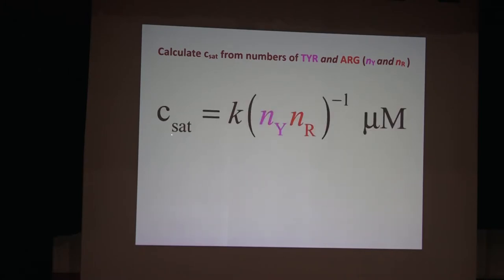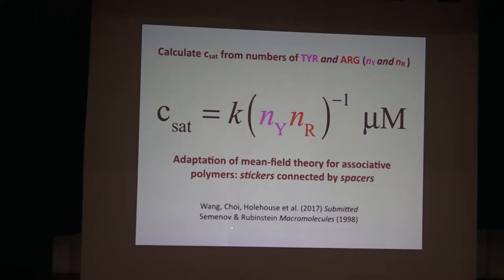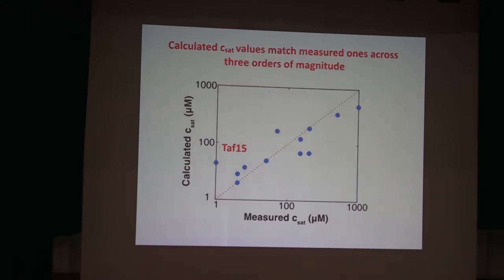You need to go to really low salt — like 75 millimolar — before you see any turbidity with the fully substituted variants. This suggests a hierarchy of interactions among these stickers: tyrosines and arginines turn out to be superior to tyrosine-lysine or phenylalanine-arginine pairs, and certainly far better than phenylalanine-lysine. We now have the ability to quantify how many phenylalanines it takes to do an equivalent job to one tyrosine, or how many lysines to do an equivalent job to one arginine. This brings us to a theory: adapting the theory of associative polymers, you can predict the saturation concentration. The upshot is a simple relationship — the saturation concentration is inversely proportional to the valence, defined by the product of the numbers of tyrosines and arginines.